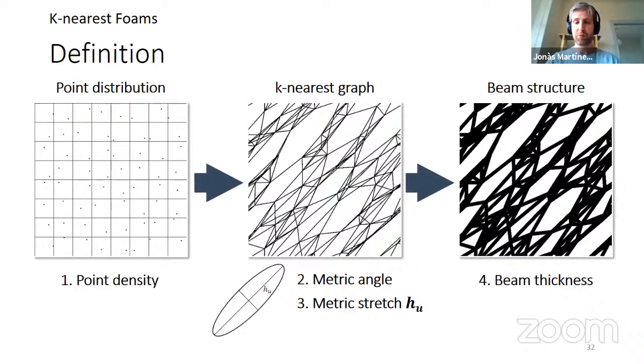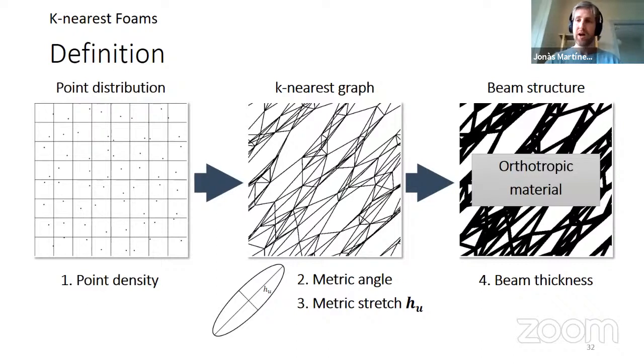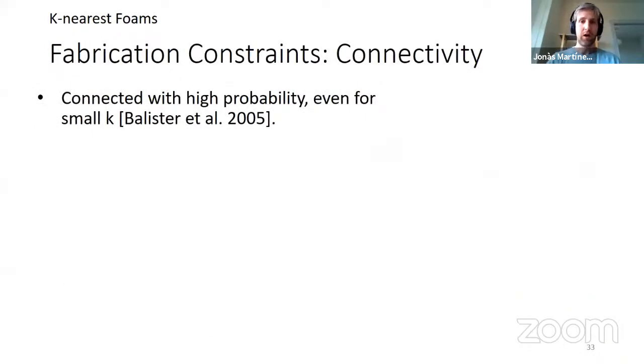As you can see, we have two parameters. One is the angle of this metric, and the other is the stretching factor. And finally, we also have the beam thickness parameter. We found that this actually gives an orthotropic material that spans a pretty wide space. I'm going to go into more detail about that later.